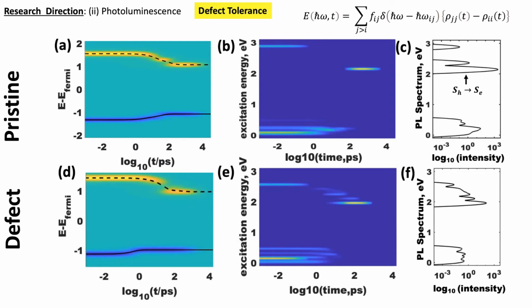And the non-radiative lifetime of this excitation is also not very short, likely because it is a shallow defect, and the recombination pathway across the gap would still need to dissipate quite a big quantum of energy that doesn't have any normal modes to accommodate it.